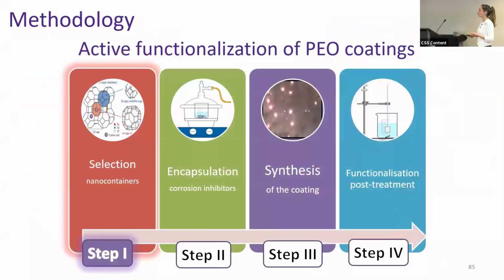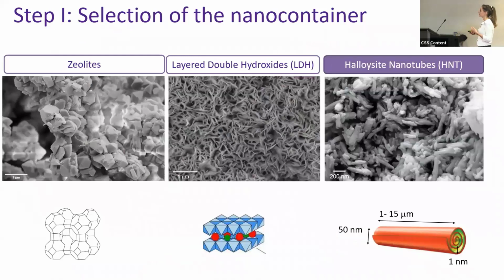So how can we achieve this objective? The first step is the selection of the correct nanocontainer. And there are different factors that we need to consider when selecting them. They should have a high loading capacity, they should be thermally and chemically stable, and they should be able to interact somehow with the inhibitor, so it can host it, and it should also be capable of releasing it when required. There are different materials that meet these requirements.